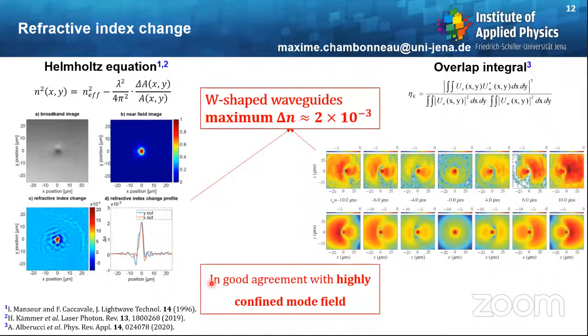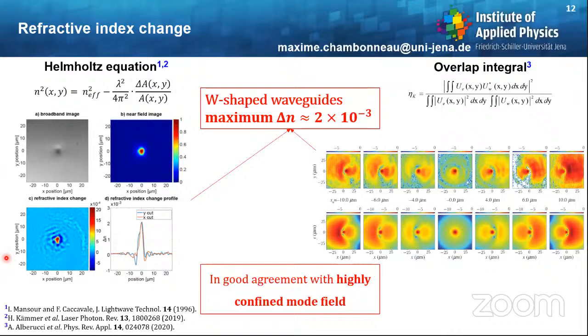Then we want to characterize the refractive index change of the material. Normally, if you can inscribe a waveguide, it means that you have a refractive index change, which should be positive most of the time for gradient index optics. To characterize the refractive index change, we rely first on the Helmholtz equation shown here, which allows us to do some simulations of the light that we should theoretically detect.